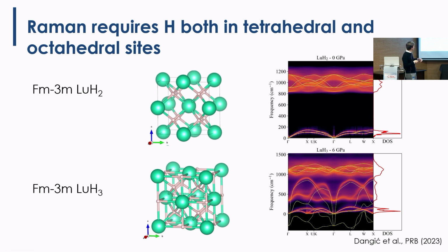Okay? So these are the phonons, okay? Somehow here in this one, you have very energetic phonons, around 1000 cm^-1. So this is somehow consistent with the high energy peak that is observed experimentally, but not with the peak that you have here at 250. All these modes, these acoustic phonon modes, are coming from lutetium.